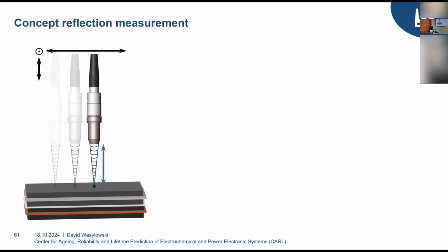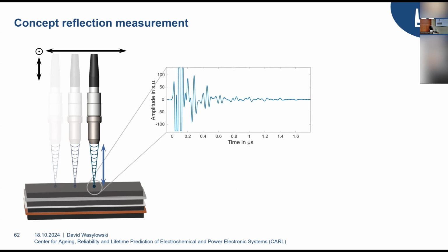Here you can see one of our reflection mode transducers that we used for this. And these reflection mode transducers have an additional benefit because they are also additionally focusing the sound wave in front of them and narrowing down the sound beam by a width of just 75 micrometers. So this increases our spatial resolution because now we can have a pixel every 75 micrometers, so we can get those really sharp images.